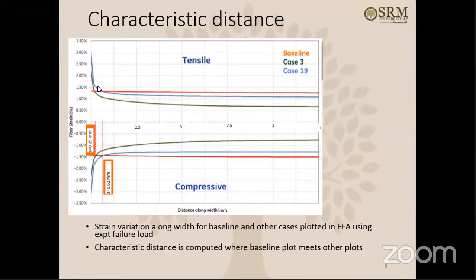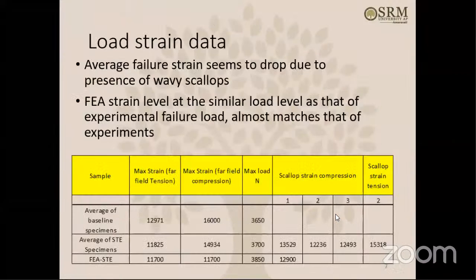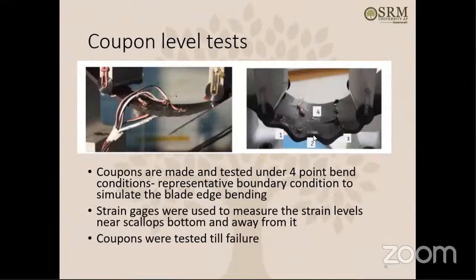Okay, so as you can see, when the baseline model meets this variation of the core, then we get some distance, characteristic distance. So what does it mean? If you look at the figure here, this is a coupon with a wavy feature, and there's a coupon without the wavy feature, that's baseline. So the strain variation along the width for this wavy feature coupon and the baseline coupon. If you measure the distance from this bottom point along the width to the inside part here, there is some characteristic distance at which the strain level comes down to the level which was there in the baseline coupon. That distance is called the characteristic distance. So we are trying to find that distance in this analysis.